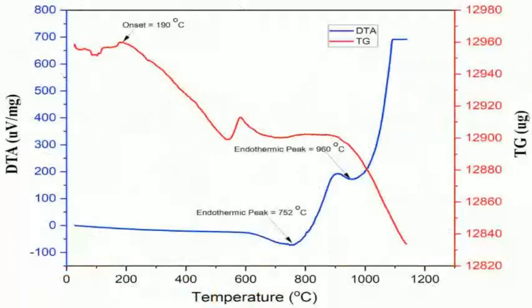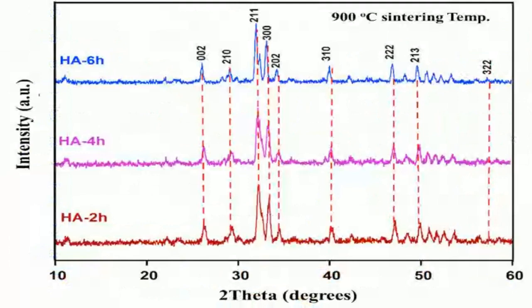So this study looked at how the manufacturing process affects this balance. Precisely. They focused on one specific step called sintering. Sintering, that's like high-temperature baking, right? To fuse powder together. Yeah, basically. You heat the material, but not quite to melting, to bond the particles. And they look specifically at the dwell time. Dwell time, meaning how long you keep it at that top temperature. Exactly. In this case, the peak temperature was 900 degrees Celsius. They tested holding it there for 2 hours, 4 hours, and 6 hours.